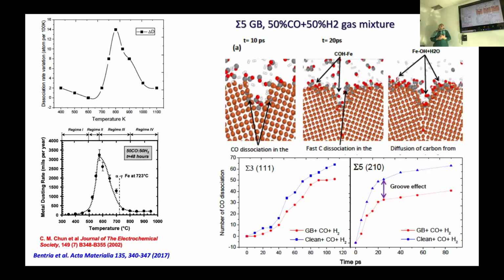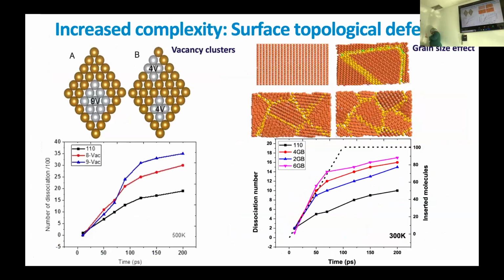However, we used the modified EAM potential to look only at the carbon diffusion and carbon cluster diffusion in iron. We looked at it from the surface and also to the bottom. But I'm not talking about it today, okay? Because today I want to focus on how we are leveraging the power of DFT calculations, what the challenges are, and how we can turn them into opportunities. This is just to give you an idea of what you can do if you have this kind of potential. We looked at 4 vacancies that are separated, and also when they aggregate, and when you have different grain boundaries emerging at the surface, what would be the number of molecules that can be dissociated, and so on and so forth.